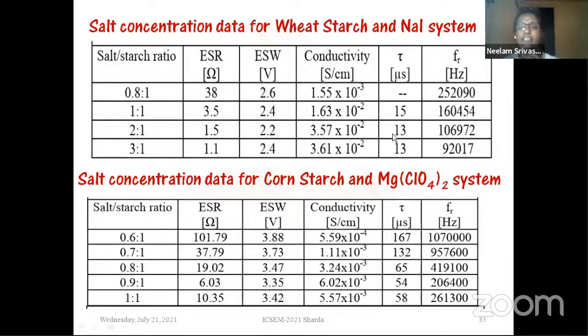Here I have summarized some of the values, how it increases. This is for wheat starch, and this is for corn starch. This is with the NaI system. This is for magnesium. And you can see the wide ESW and low resistance: as you increase the salt concentration, ESR is low. But better ESR is observed with NaI, which is very obvious, because sodium is much lighter than magnesium. So magnesium must have slightly slower transport in comparison to sodium. The same can be observed from the tau value also. For magnesium, we have a little higher tau value, whereas for sodium, we have lower.